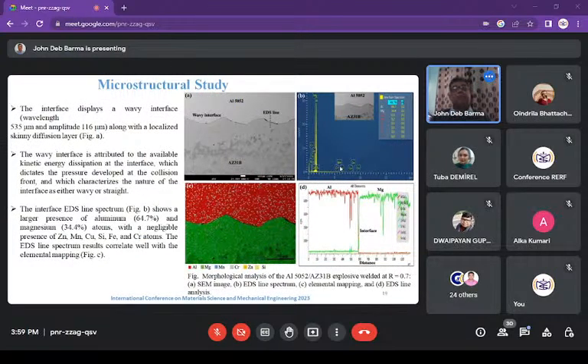Now, if we look at the morphological analysis of the weldment that is welded at a loading ratio of 0.7, this shows the SEM image, B shows the EDS line spectrum, C shows the elemental mapping, and D shows the EDS line analysis. So here, as you can see, this interface appears wavy, right? The wavelength here we have seen to be 535 micrometer and amplitude of 116 micrometer. And this wave is along with a localized skinny diffusion layer that is appearing here.